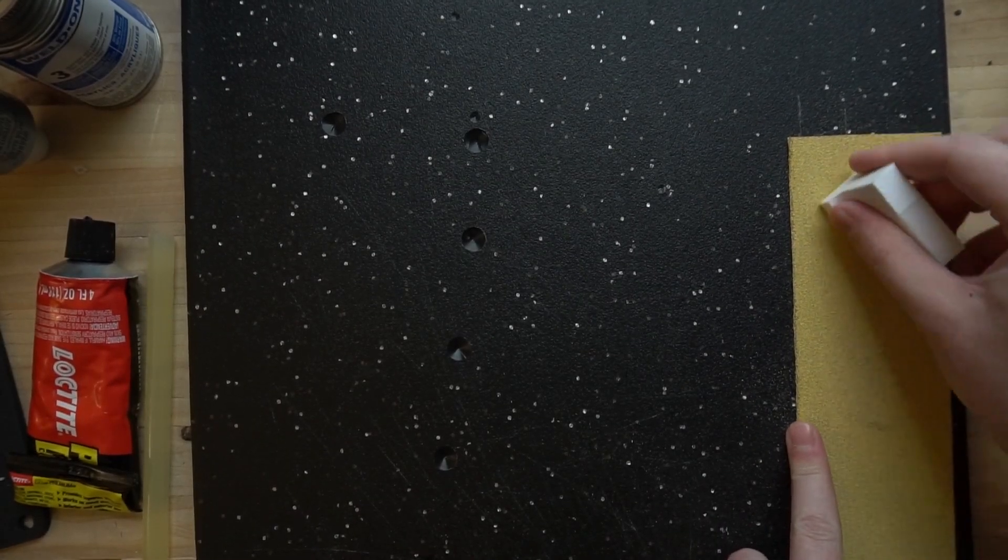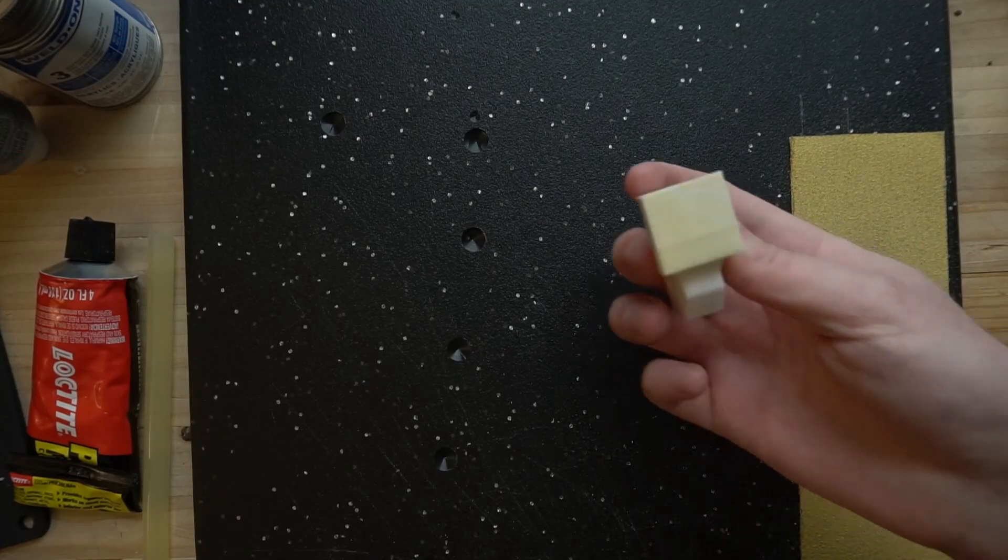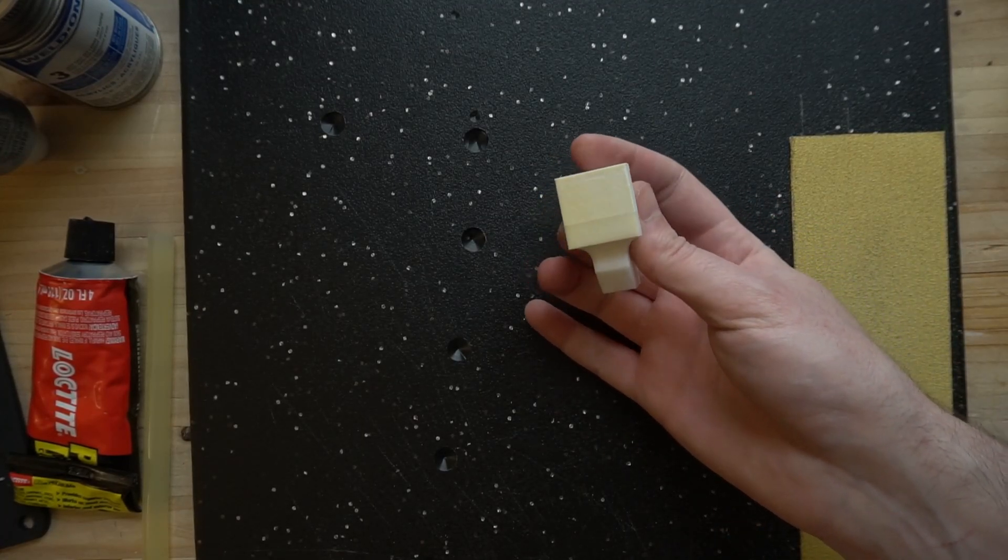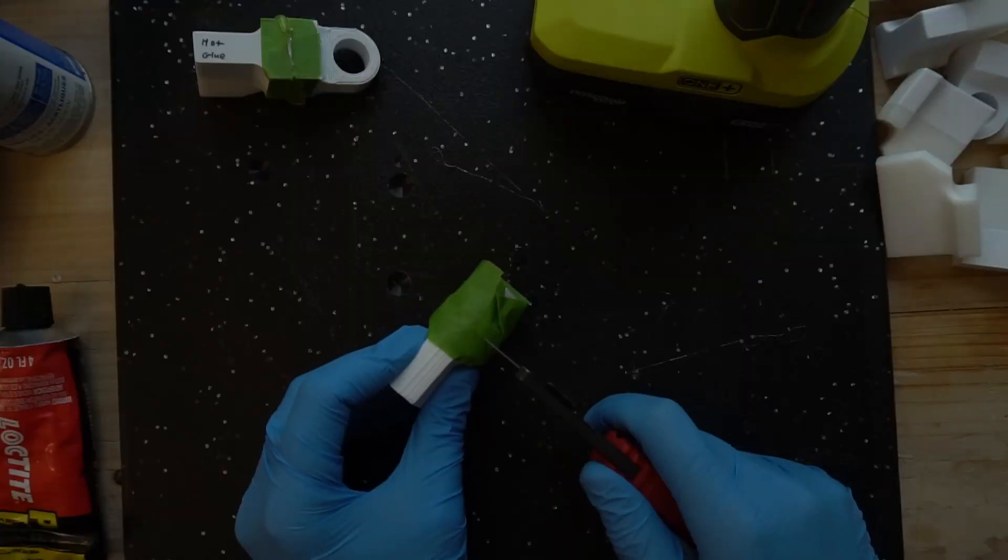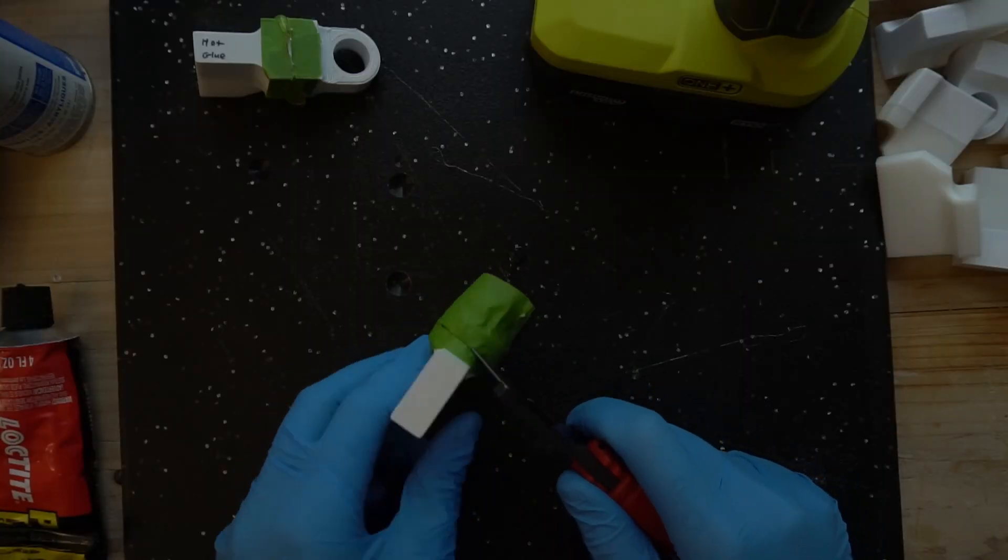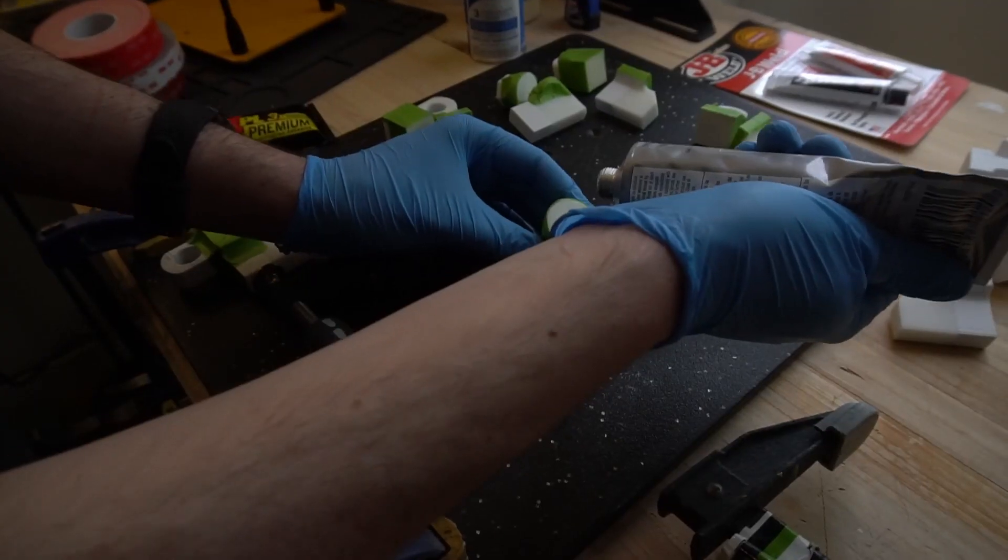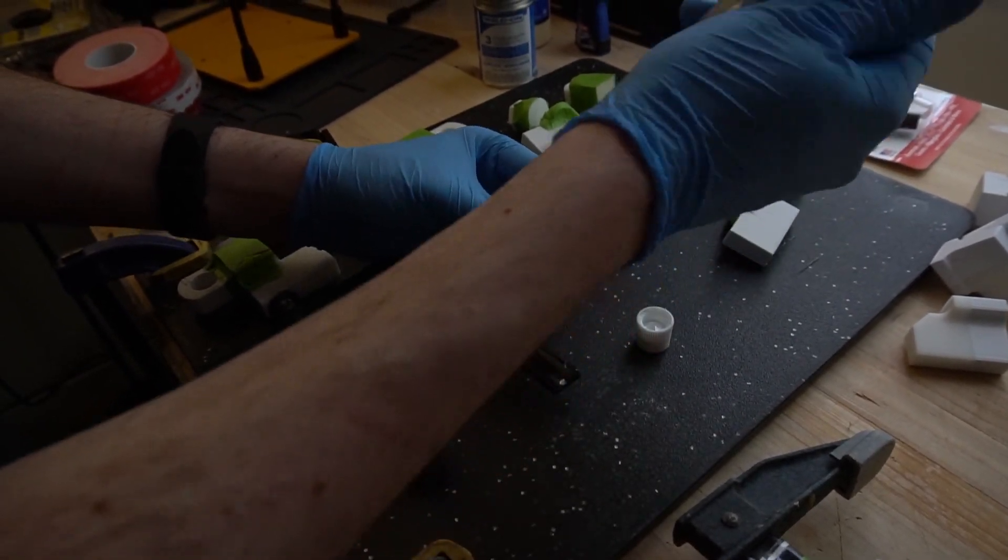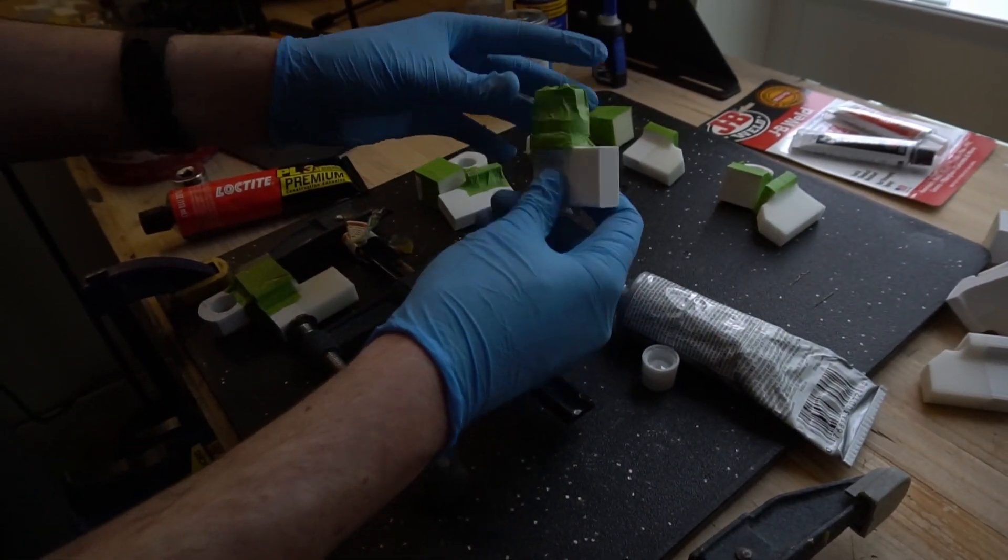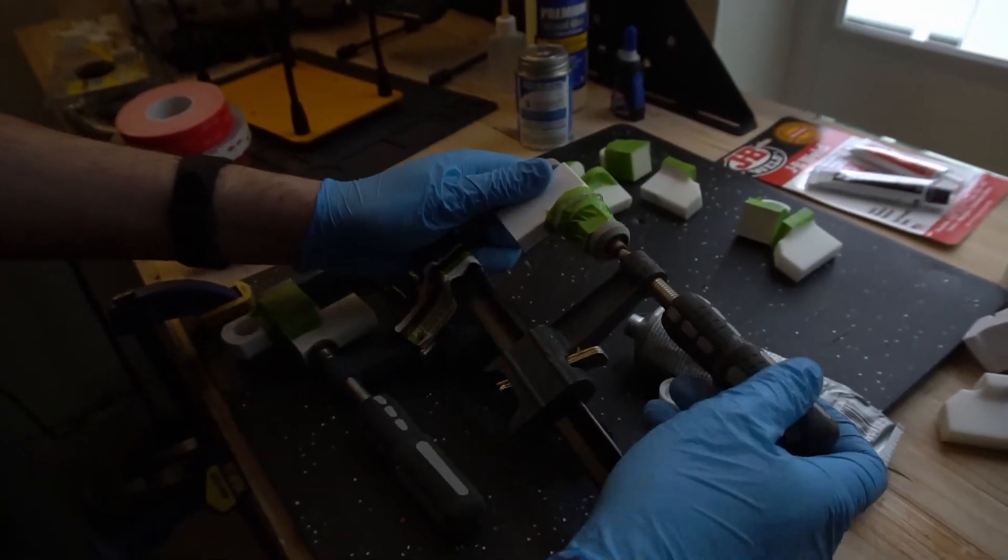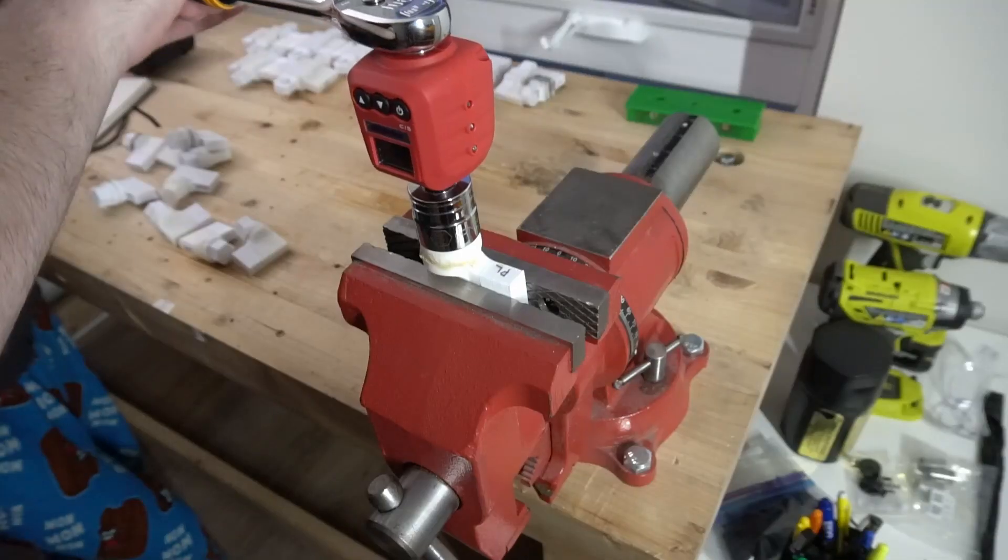All 3D printed parts were first sanded with 80 grit sandpaper to remove any layer lines and to provide an ideal surface for the glue to adhere to. For more viscous adhesives that would squeeze out, tape was first applied around the joint area and then cut with a knife. The glue was applied and left to dry. After, the tape along with any squeeze out was removed before testing occurred. All parts were clamped and given one week of dry time before testing was performed.